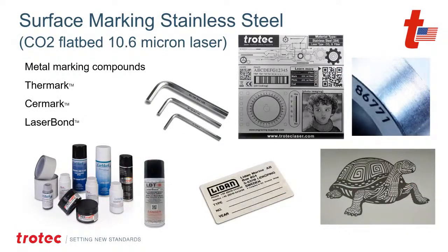So let's get a little bit into some of the more common applications for this. As I've mentioned a little bit, stainless steel marking with the metal marking compound is probably the most common on the flatbed systems. Metal marking compounds, including Thermark, Cermark and LaserBond, those are the top 3 materials out there, actually fuse to the surface of the metal, and you get a nice high quality black fused mark. This is not as durable as a fiber or a Galvo fiber laser because it is not etched or engraved into the metal. It is more of a melted glass fused surface onto the surface of the metal.